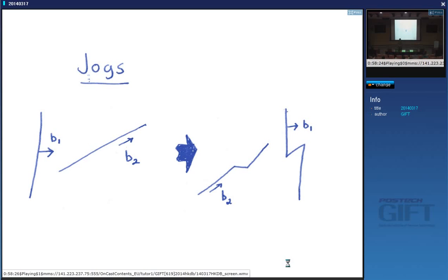So what this says is that the interface for martensite must not have more than one set of dislocations. Because if you have more than one set, they will interfere and make the interface sessile. So it's a very important result that the interface between martensite and austenite must have just one set of dislocations. It cannot have more than one, otherwise they would interfere with each other and therefore make the interface sessile.